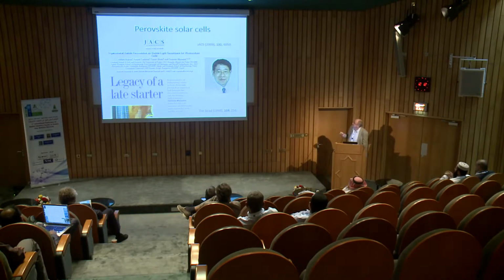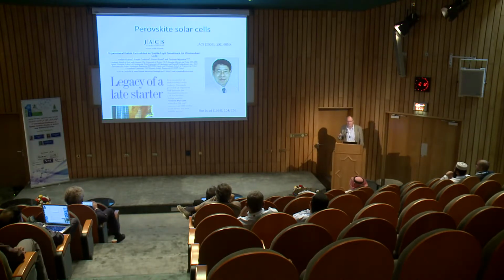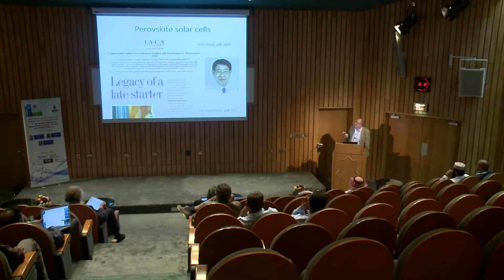an organic-inorganic perovskite. Early 2000, I think, with a student, it was not so successful, so he tried. He started to talk about it in conferences 2006, as far as I know, saying that he did some perovskite with about 2-3% efficiency, but he had to be very quick to run to the lab to measure the efficiency, because they were stable not for more than about 10 minutes, just to have time to do the measurements, and then they were dissolved in the liquid electrolyte. So that was the problem, and finally he published a paper in 2009 describing the perovskite at 3-4% efficiency.